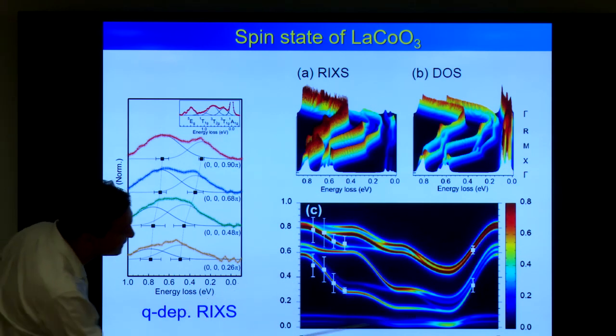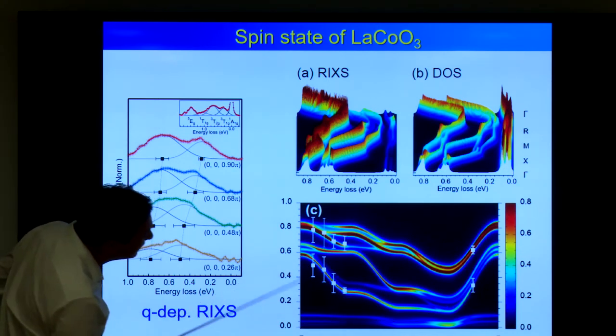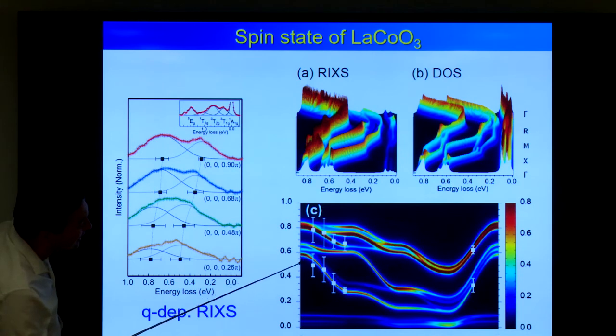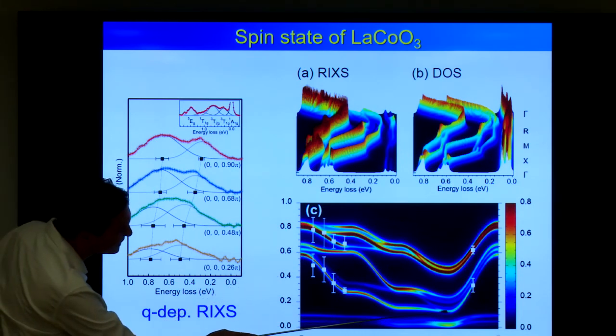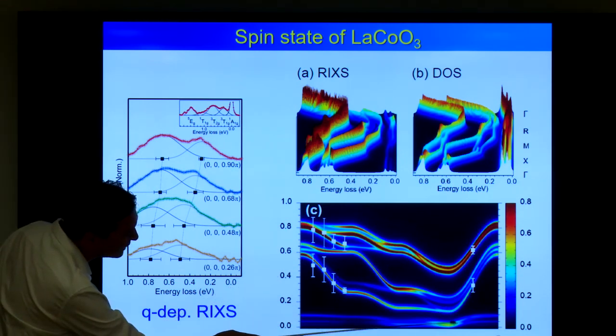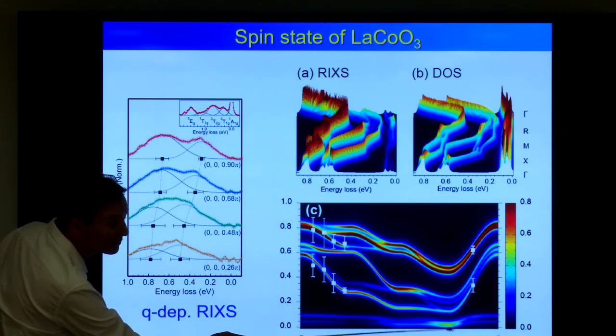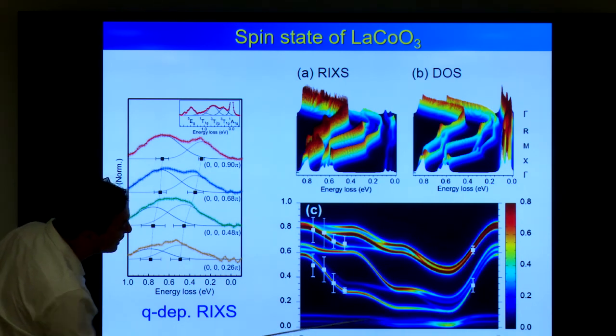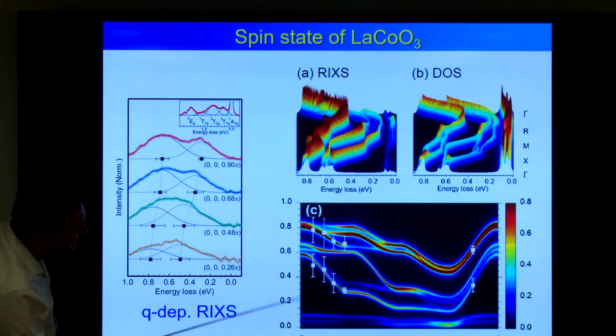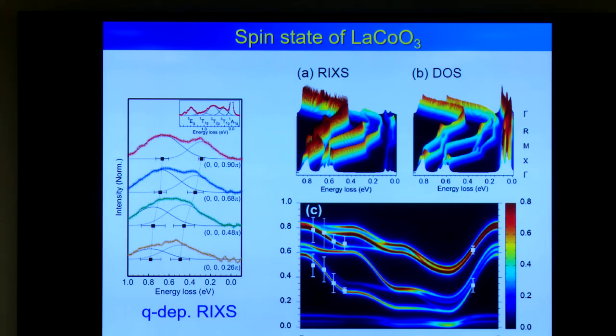It's between 0.6 and 0.2. So it doesn't really touch 0, but you can see here that it starts to mix. So here the ground state becomes a mixture between low spin and intermediate. These are the 4 data points. Every data point took 24 hours on the ADRESS beamline at the Swiss Light Source. So this was a whole week of beam time.